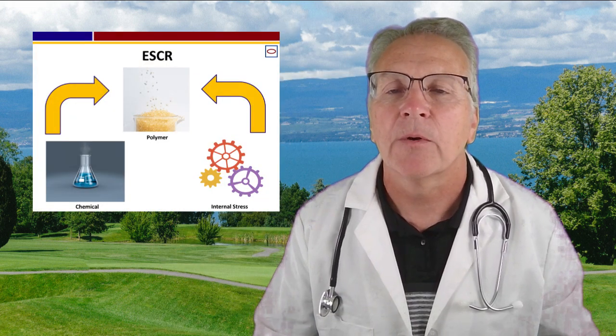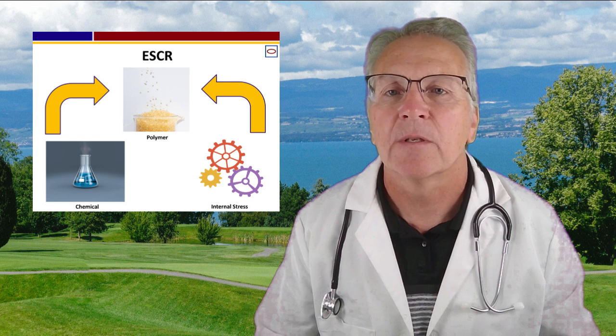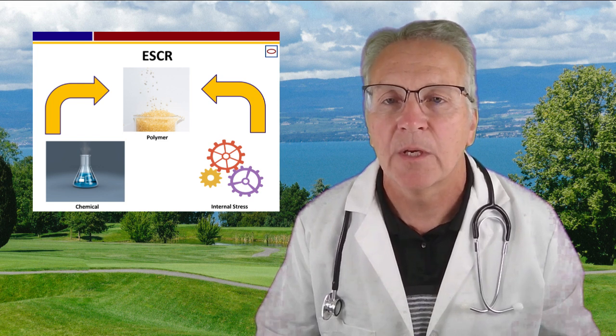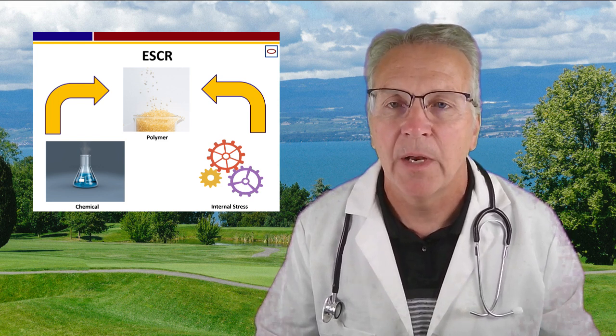And for an explanation, as the water flows across the part, the high-density polyethylene grade cracks through brittle failure due to the built-in part stress from molding, which did not happen in air. As shown on your screen, environmental stress crack resistance is a function of the specific material, stress, and chemical combination.